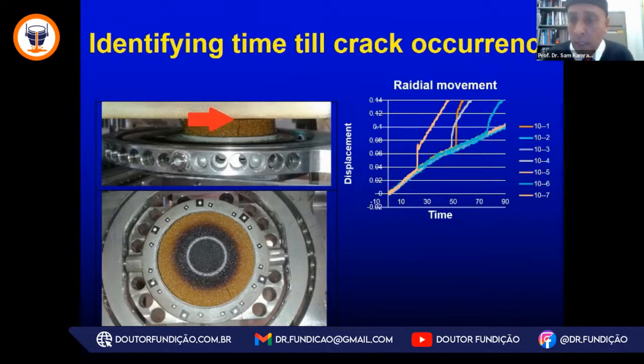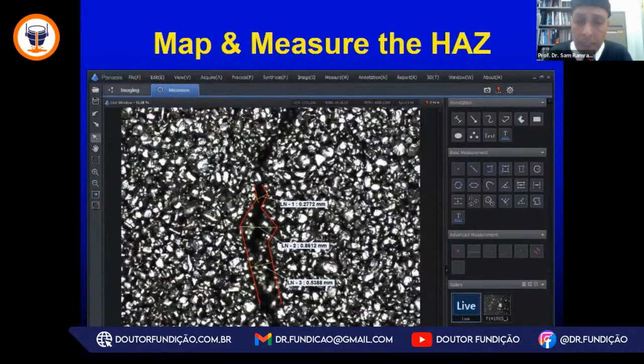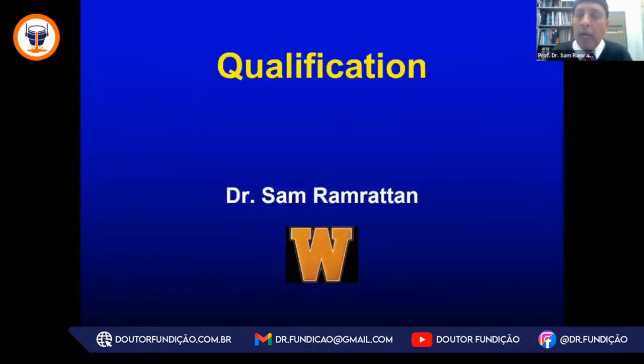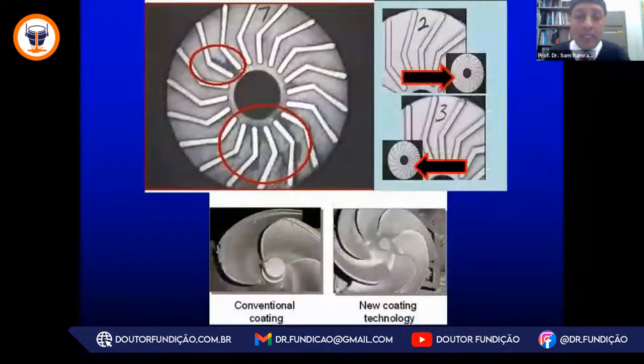If it freezes, then no problem from the crack, maybe some distortion issues, but ultimately we will not have the problems that could be metal penetration or veining. Those are the important issues. And for that reason, I am suggesting that we must qualify the sand binder system.